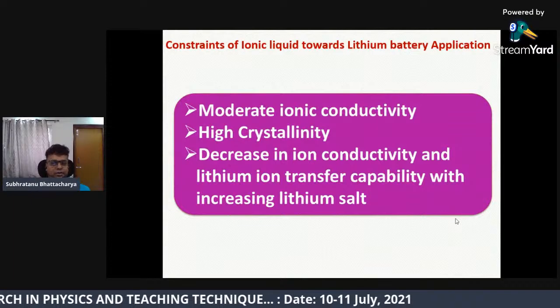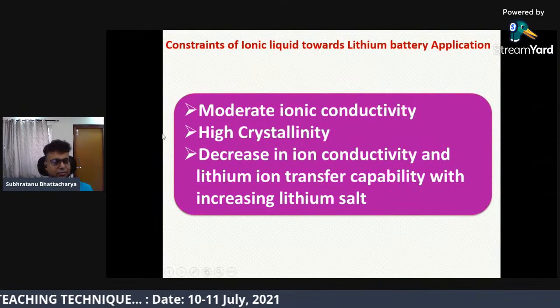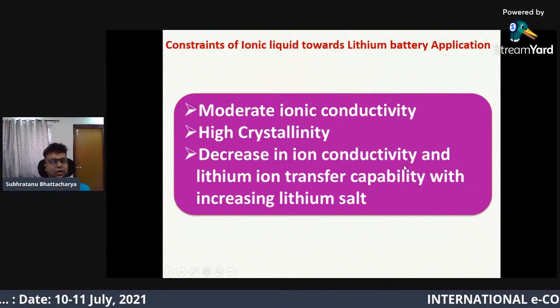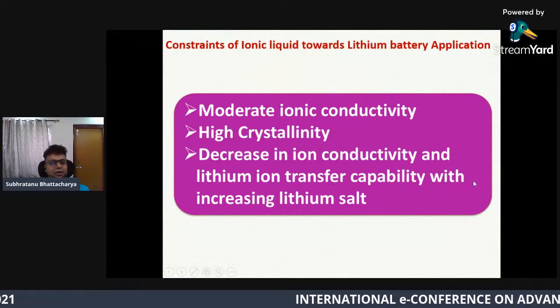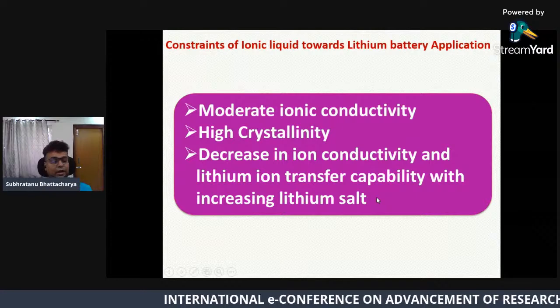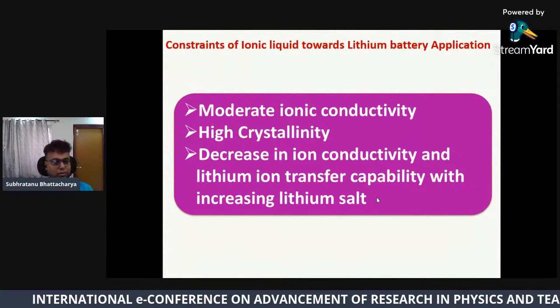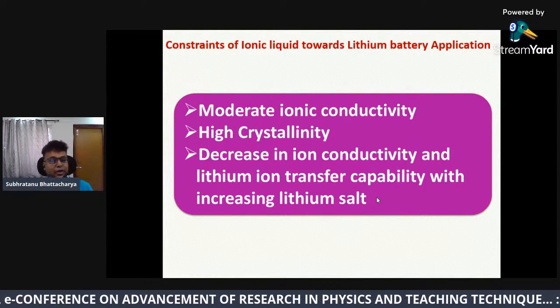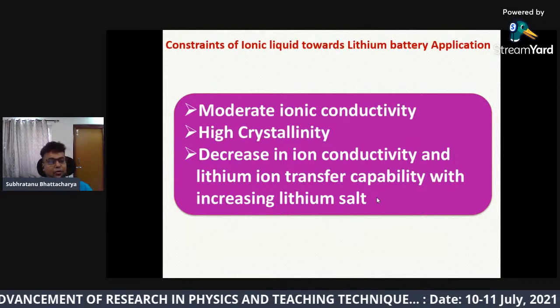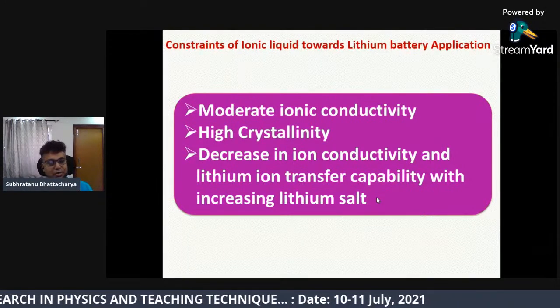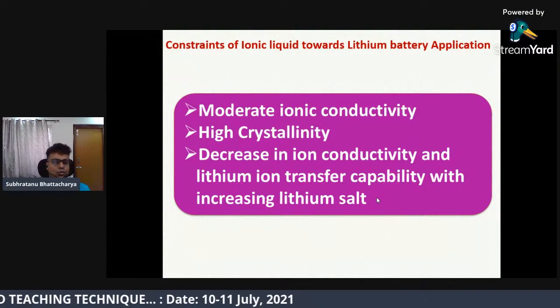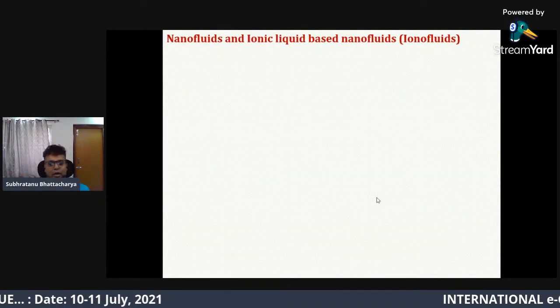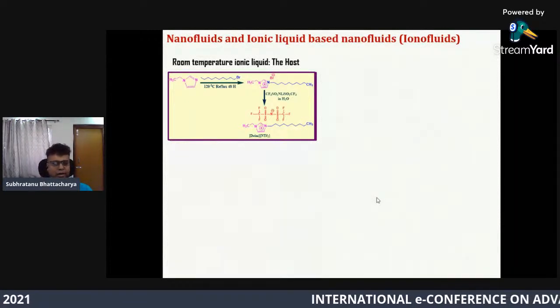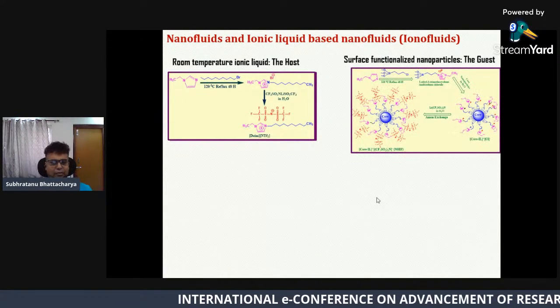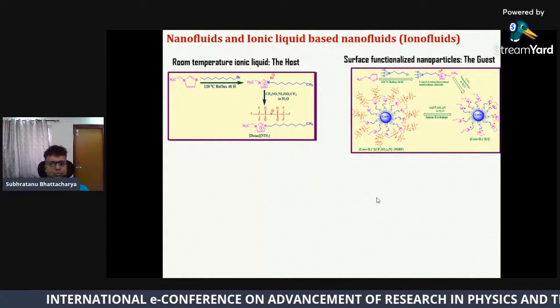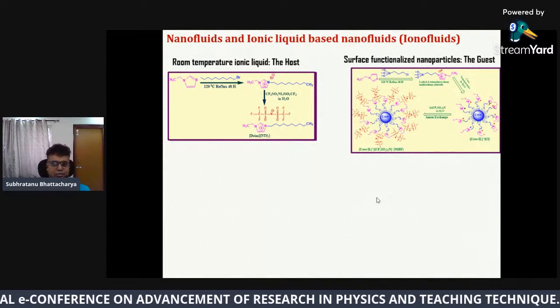But there are some constraints. Moderate ionic conductivity first, high crystallinity, and a decrease in ionic conductivity and lithium ion transfer capability with increasing lithium salt. Because if you add lithium salt in that solvent, the viscosity becomes very high. You know, viscosity is detrimental for ion movement. So if you increase the viscosity, your ion mobility will slow. We have done some work on that. I'm not going into detail because that may be difficult to understand, specifically for the undergraduate students.